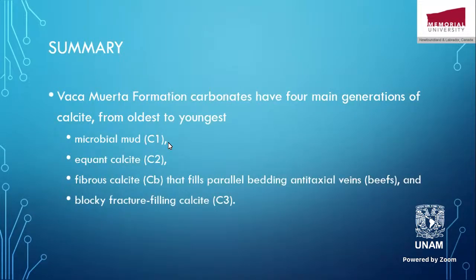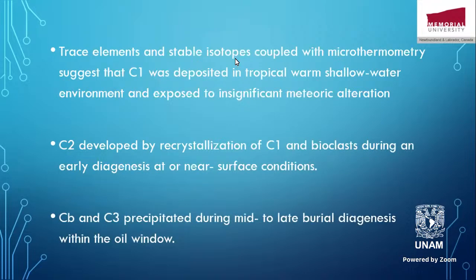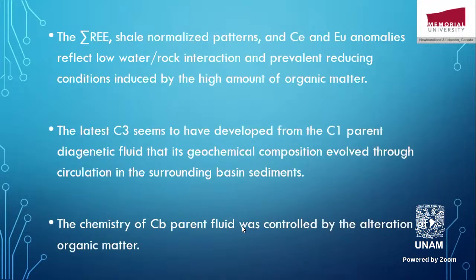In summary, the carbonates in the Vaca Muerta Formation have four main generations of calcite: C1, the microbial mud; C2, the equant calcite; the fibrous calcite, beef cement; and the last one, the fracture cement, C3. The trace elements and the stable isotopes, coupled with the microthermometry, suggest that C1 was deposited in a tropical warm shallow water environment and exposed to insignificant meteoric alteration before diagenesis. C2 developed by the recrystallization of C1 and bioclasts during early diagenesis at near surface temperature and pressure. The beef calcite and the C3, the fracture calcite, precipitated during mid to late burial diagenesis within the oil window, because there were oil traces in those cements.